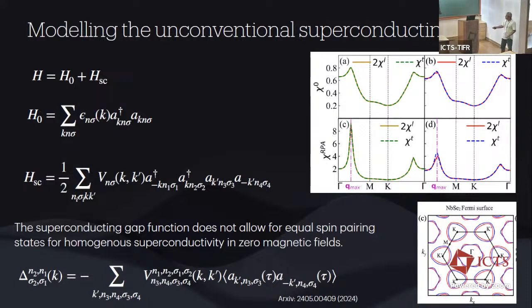So this particular piece, we calculate along the lines of looking at a spin fluctuation mediated pairing mechanism, primarily summing up all the bubble and ladder diagrams to include spin and charge fluctuations within our model. So you get a momentum dependent pairing interaction in the repulsive channel coming out from here. Now, I won't go into the details of it, but you know, as Brian also talked about a couple of days back, that this pairing interaction is proportional to the charge and spin susceptibilities in your system.